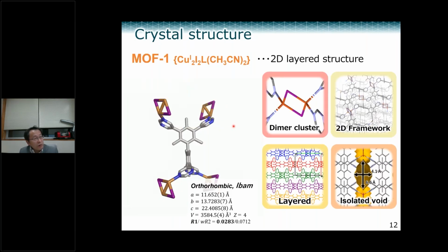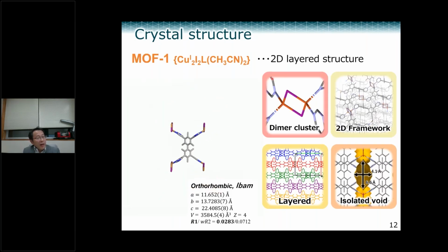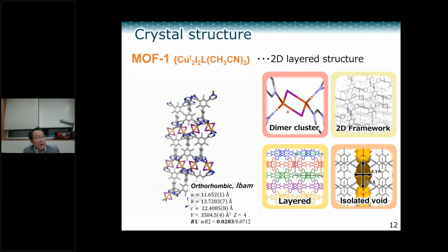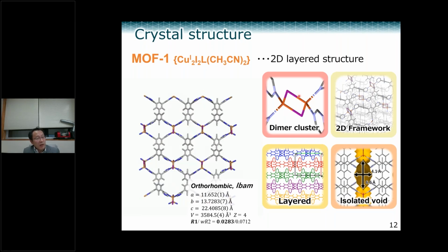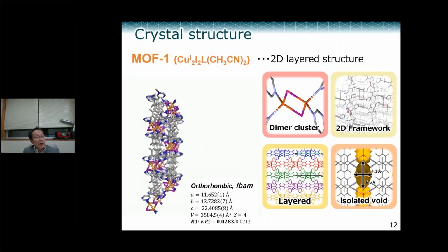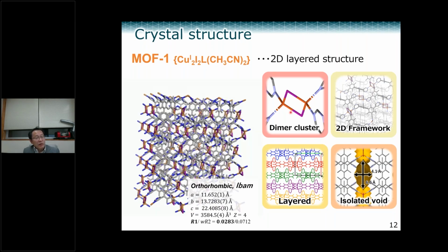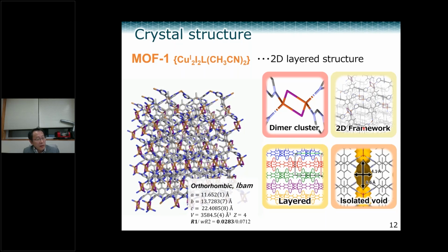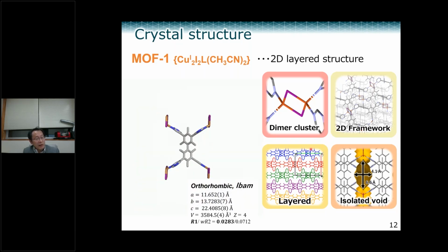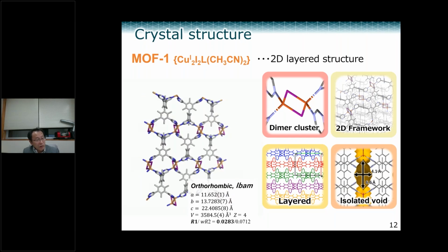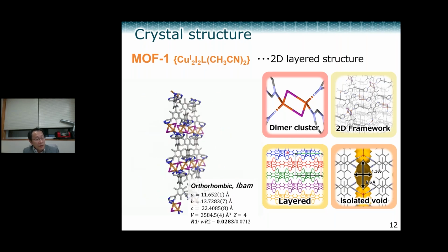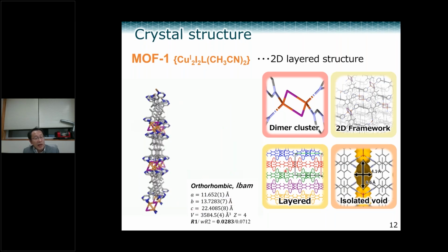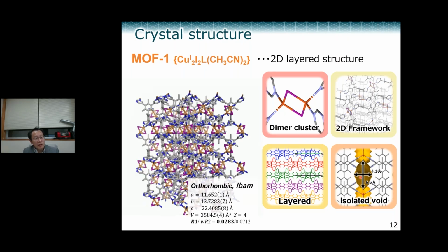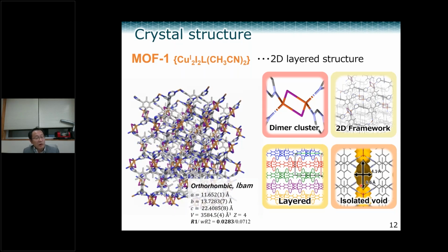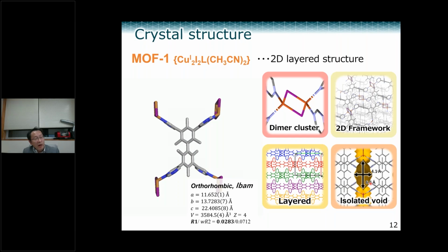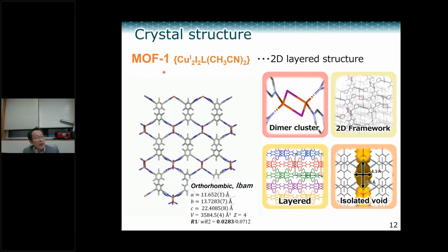Okay, let me explain the structure of MOF-1 first. MOF-1 has a copper iodide dimer as a connector, like here. This copper dimer forms a 2D sheet, a 2D framework. Then the 2D frameworks stack on each other to make a 3D crystal packing. Basically it is a 2D layer structure. If you look between the layers, you can see an isolated pore, which is quite small, with dimensions of 4 angstrom and 6.6 angstrom. From now on, I call this network 2D MOF, or MOF1.